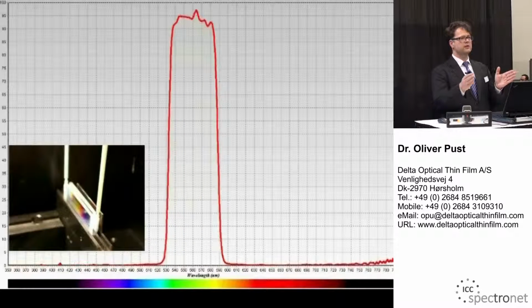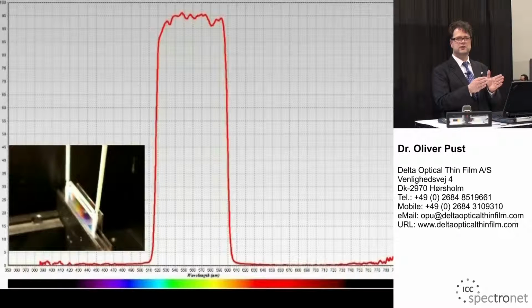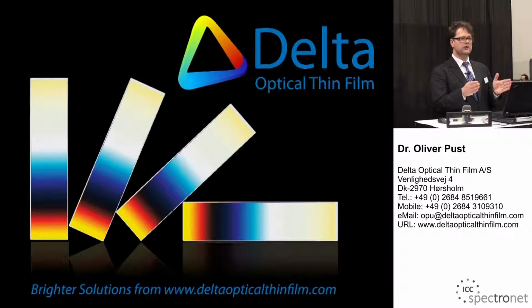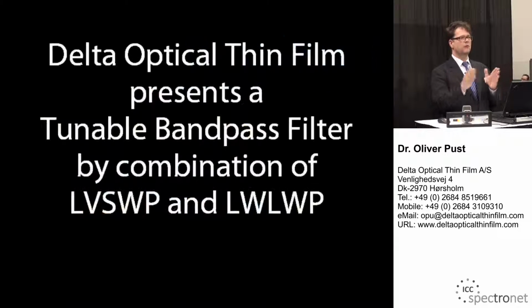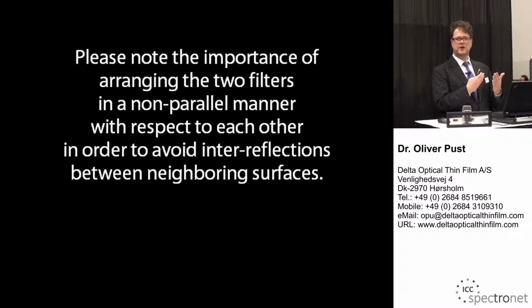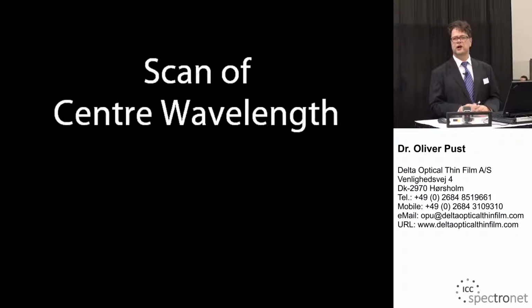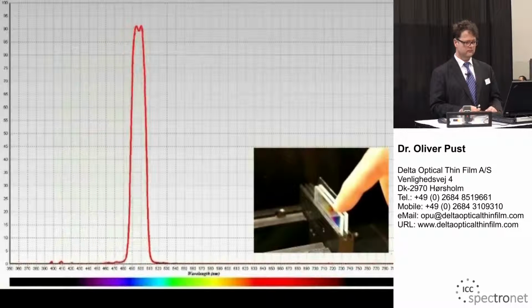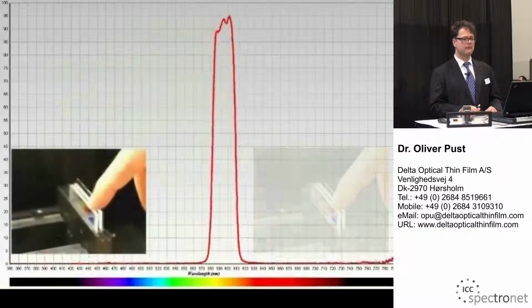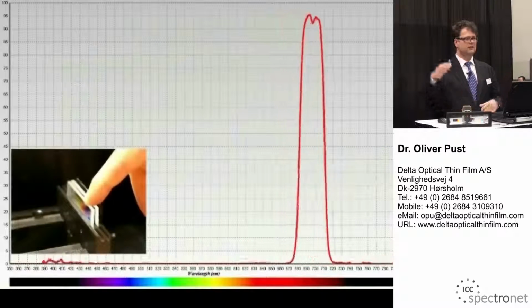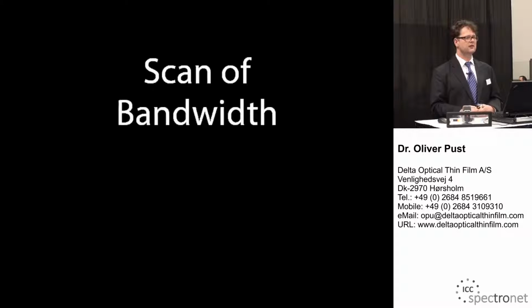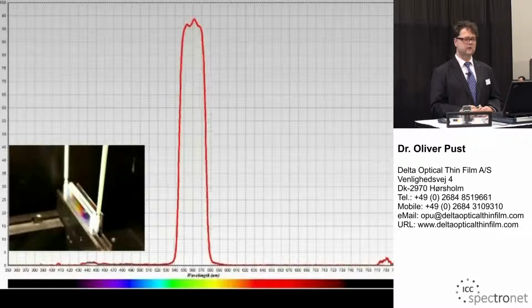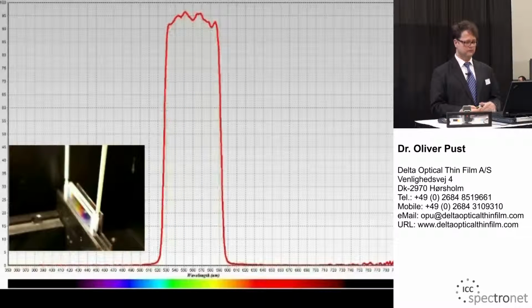And in the second sequence, you can see when we move the filters in opposite directions, we adjust the bandwidth, again continuously between as narrow as 10 nanometer and 150 nanometer or more. So with just two optical components, you have any bandpass filter between 300 nanometer and 850 nanometer. And you can also see the top line is 100%, so very high transmission level throughout the complete tuning range.